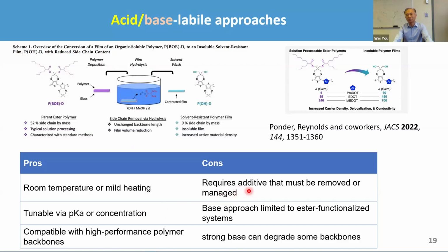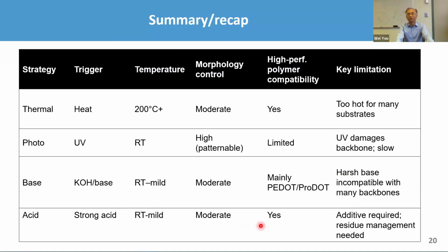But then the bad news is that you also need additives. And unless you're using a water approach, you may be able to get rid of them in the solvent. But in many cases, they may actually stay in the film, which is going to affect your morphology and many other things as well. And then it's rather limited to ester functionalized systems. Okay, sometimes if you're using a strong base, you can degrade your polymer film and the backbone as well. So this is sort of the summary of the approaches the community has attempted in the past 20 years: thermal, photo, base, and acid. Most of the approaches you can think of, we have already tried in the field. Nothing is perfect. You have to choose the right one depending on your intended application as well.